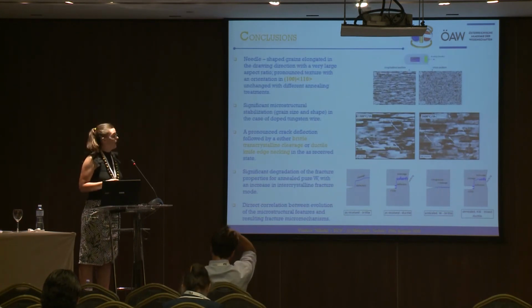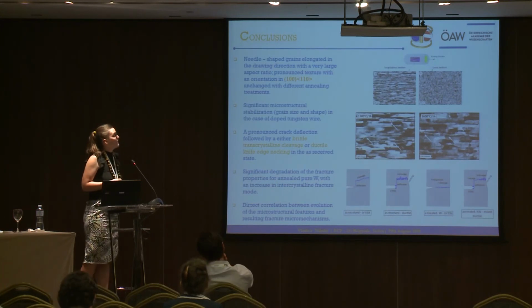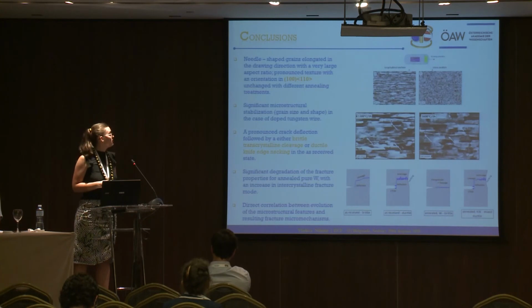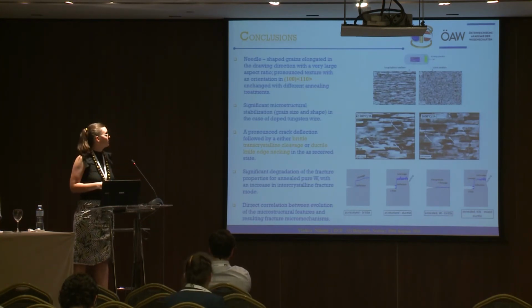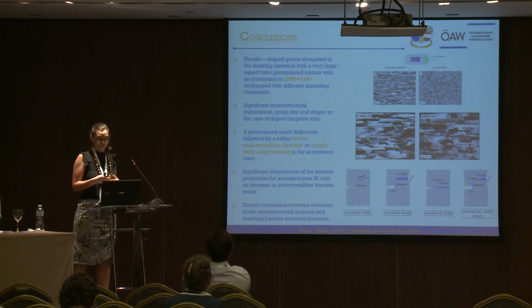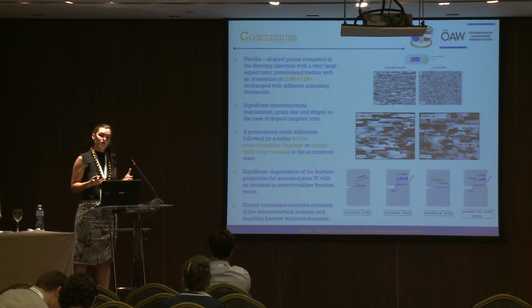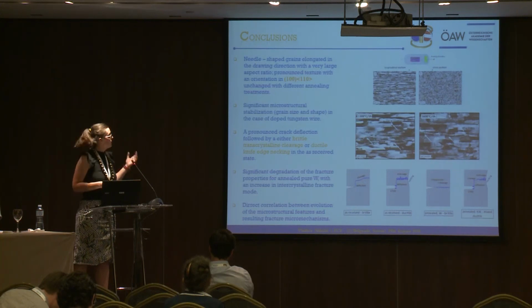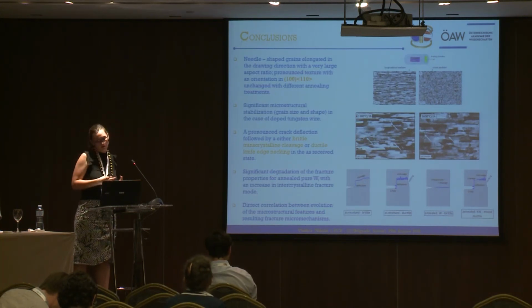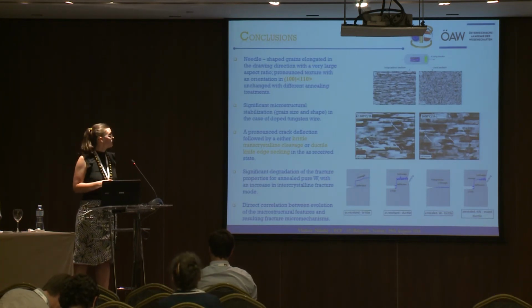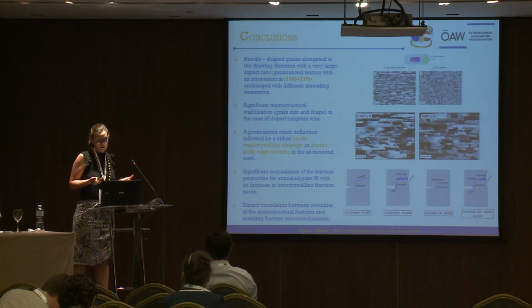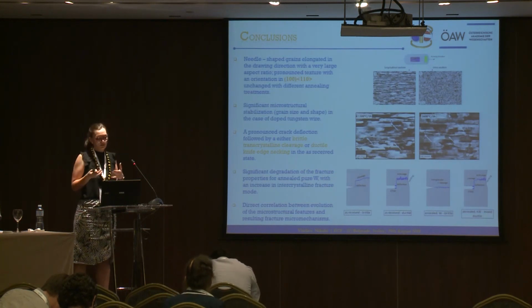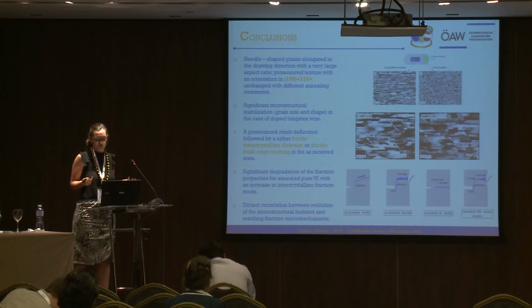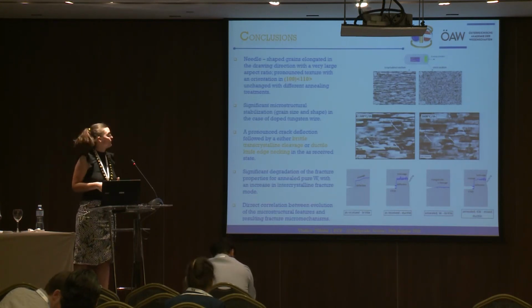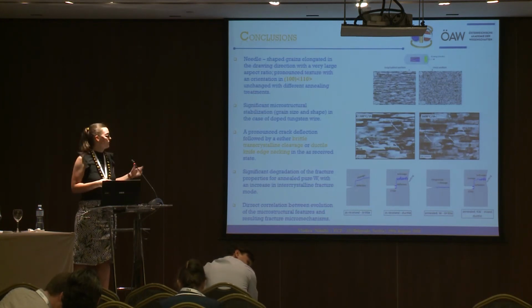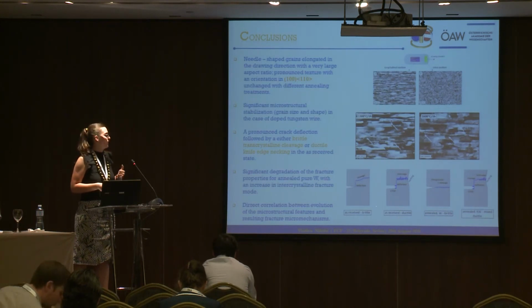Okay, so to sum up, essentially the three main points is that these kind of materials have very unique microstructure from the production, right? So high degree of deformation results in this elongated structure. And if we submit it to various heat treatments, substantial changes occur in the case of pure tungsten. And we also could see that this is successfully shifted to higher temperatures in the case of doping, so the doped material. And a very important aspect, and the most important aspect, is that microstructure, at least for tungsten, is severely controlling the fracture process. So it's very influential. And we could directly see that from the observed appearance of the microstructure at particular temperatures, which then resulted in one of 4 appearing failure modes.